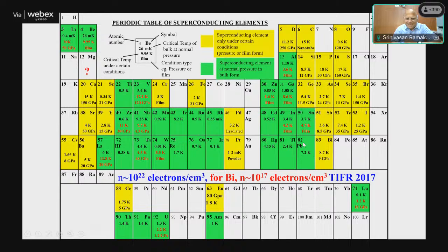Of course, the only element which is very unusual is bismuth. Bismuth under pressure is superconducting, as mentioned by Dr. Manoj Kumar. Bismuth is strange compared to other metals in the periodic table because its carrier density is 5 orders of magnitude less than that of normal metals, which have 10 to the power of 22 electrons. So people thought that bismuth was not going to superconduct, and certainly, if it did, it would not be by the BCS theory, which I am going to tell you about in the next class. We showed that it is superconducting below 500 microkelvin, and the mechanism is different there.